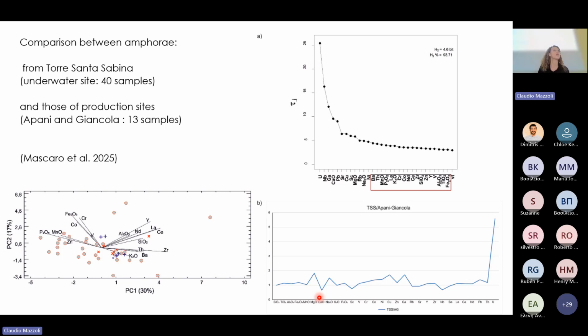What is a method to solve this problem? Not to work with absolute values, but divide all the chemical elements by the element which has a lower variability, transforming all the data into what we call log transform ratio. So we divide all the chemical elements by the element which has the lowest variability and transform everything in a logarithm-based step. Right? This is a way to solve the problem. And in this way, we experimented with the data and we have seen, in the example I reported to you, that the samples which experienced the underwater environment, which are the circles, overlap with those from the land, represented here by the blue crosses.